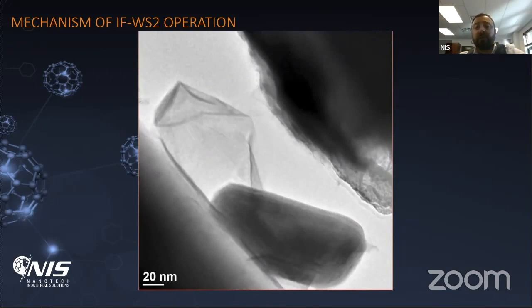So in this short video, you pretty much saw friction reduction, that's your exfoliation mechanism. You saw the shock absorbing or extreme pressure properties of this material, by absorbing the shock by compressing and having high elasticity. That is very important when we talk about extreme pressure, to talk about both dynamic and static extreme pressure. Because when we're measuring extreme pressure with the 4-ball, which is a typical test for extreme pressure, we are running at a certain condition with a load applied slowly on the system, but we don't really observe impact resistance of the system. So it is very important to know that these particles protect from regular extreme pressure or static load, as well as dynamic load like shock.